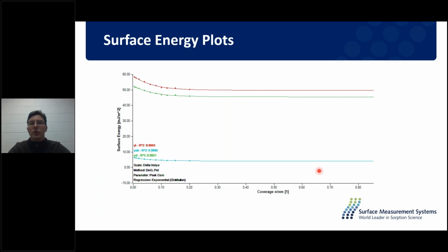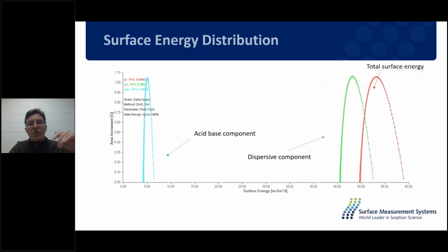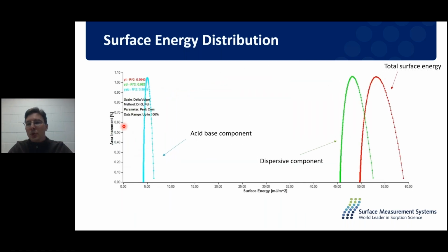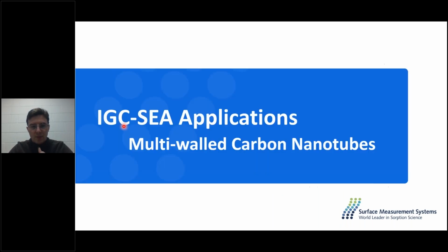And I form a profile that looks like this. So here we see in our green line, this is our dispersive surface energy. With our blue line here, this is our acid and base surface energy, or our polar surface energy. And the red line here is our total surface energy. So from a simple experiment, I now have formed 3 different surface energy profiles. And I can turn each of these into a distribution to get the population of each of these energy levels.